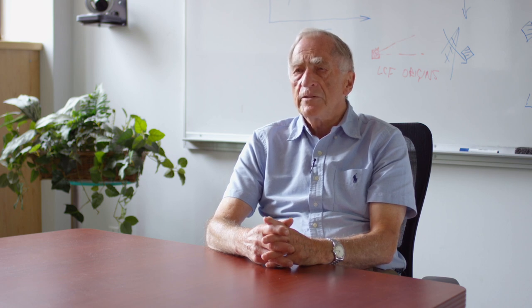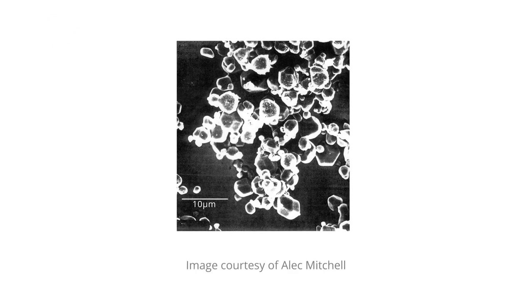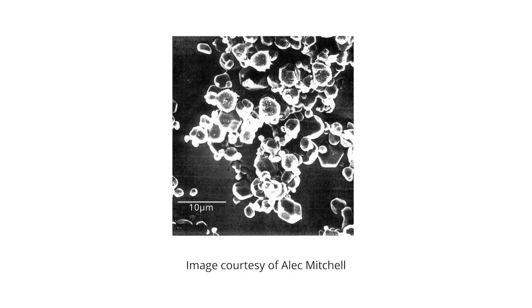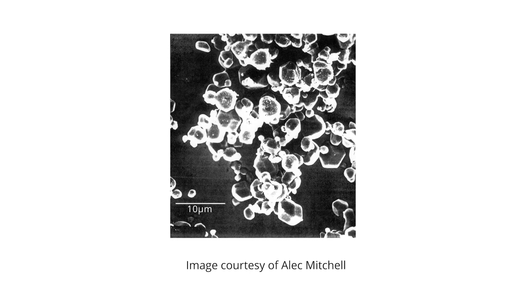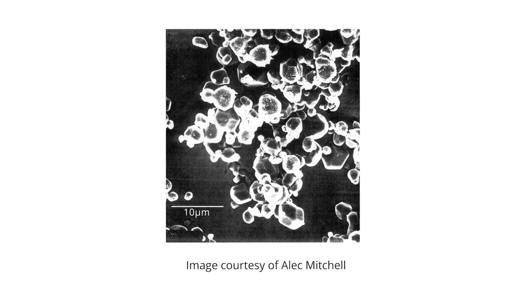And we found that they were being glued together by titanium nitrides. So if we looked at the inclusion collections in three dimensions, we found oxide particles which were stuck together in a three-dimensional network by titanium nitrides. So our conclusion was that titanium nitrides were an important part in determining the behaviour with respect to the oxide inclusions.